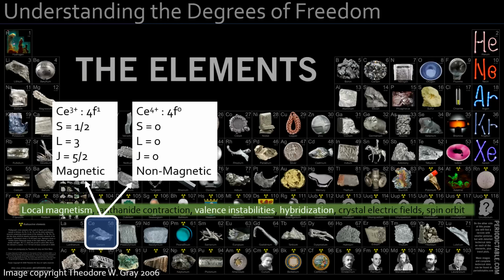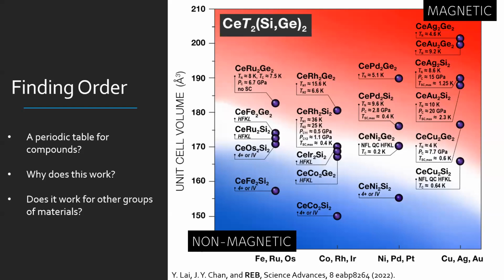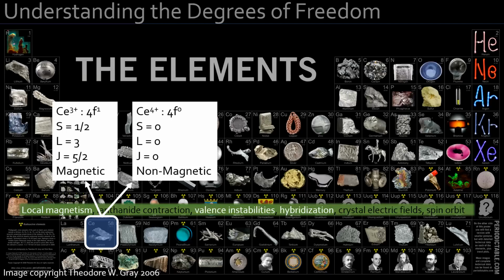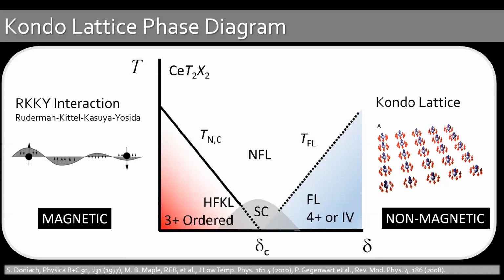Okay, so people have worked on cerium compounds extensively. And you can see that this really does make sense from what is known about them. And the first thing we want to know is that cerium can take two valences, 3+ and 4+. If it's 3+, it has one F electron in the F shell, and the S, L, and J values are shown here, which gives us magnetism. If it's 4+, there's no F electrons, we wind up non-magnetic. So it's immediately clear why there would be some that are magnetic and some that are non-magnetic. Okay, but we can go further.